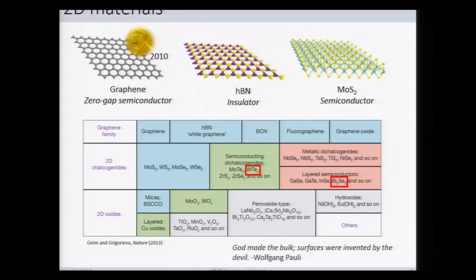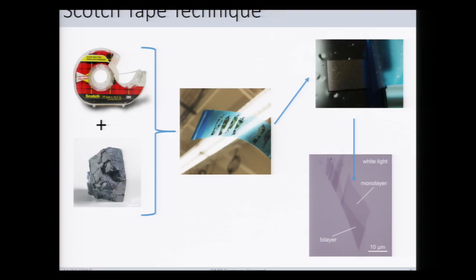One of the conceptually amazing aspects of 2D materials, not that it necessarily makes research easy, is the so-called Scotch tape technique that many of us are probably familiar with, where we simply have a rock and a piece of tape, and you put the tape on the rock, and you get these thin regions, which we can then place onto a silicon chip. And once we peel the tape off, you see this fuzziness.